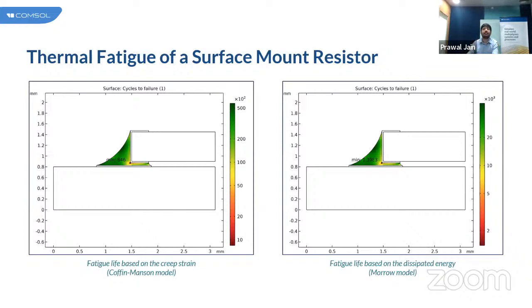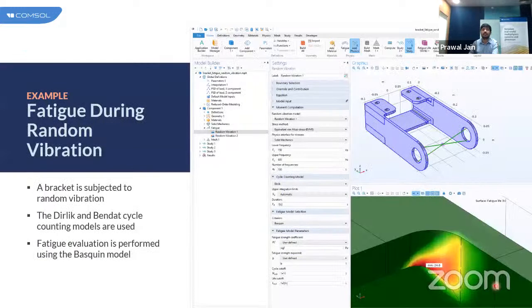Herein, the fatigue life is based on the Coffin-Manson model as well as the Morrow model, which is based on the dissipated energy. We can see that the strain-based fatigue gives a lifetime of approximately 800 cycles, while the energy prediction gives us 1,400 cycles, which means that Coffin-Manson gives us a more conservative fatigue life of this surface mount resistor.